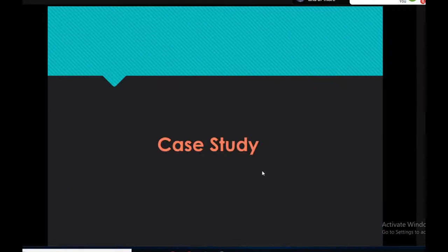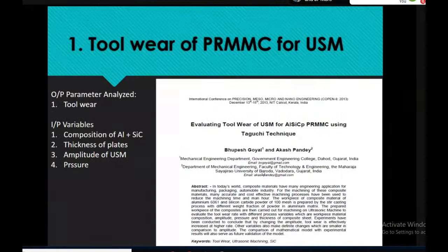So let us discuss some case studies I have, what we did till now. This is what we did in 2012, where we were evaluating the tool wear of ultrasonic machining for an aluminum silicon carbide metal matrix composite. The output variable we were trying to measure was tool wear. The input variables were the composition of aluminum plus silicon carbide, let's say 5%, 10%, 15%, the thickness of the plates, the amplitude of USM, and pressure. So these are the 4 variables we had, and we tried to measure the tool wear.